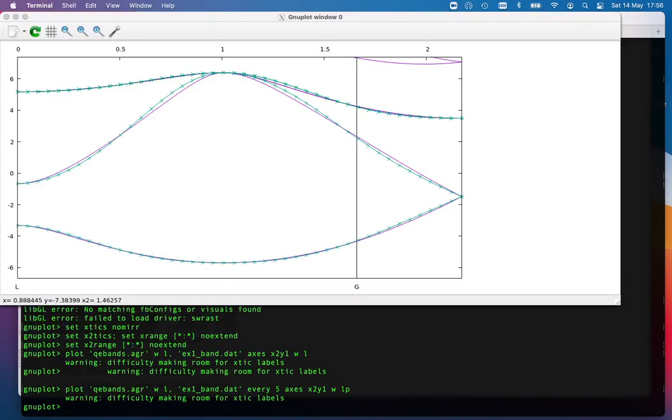So what we've got is the purplish color are the QE, so that's full SCF accuracy, full plane wave calculation, and the crosses are coming from the Wannier interpolation. So the lower S band extremely good, the upper band is very good. Everything is reproduced at gamma. Well, that's in the original mesh, so we'd expect that to be the case. And we've got a little bit of deviation in the curvature of this band here. It's not bad, but it's not great. Why is that? It's because we constructed our Wannier functions from a 4x4x4 grid. If we went up to 6x6x6 or 8x8x8, this agreement would get better. Certainly probably by 6 you'll have a difficulty noticing it on a diagram. The convergence, as I may have mentioned earlier, is exponentially good. Okay, so that's all nice.